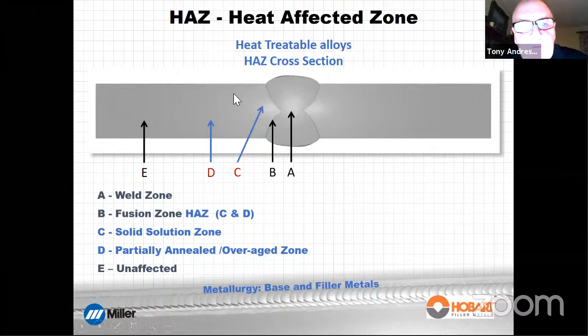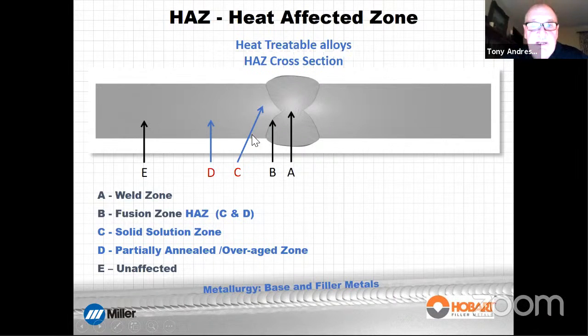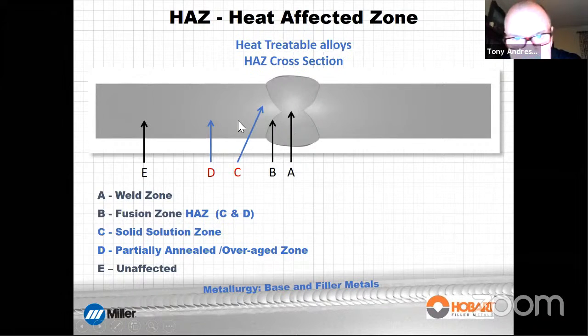So the rule here is to keep the heat down as low as possible if you want to get the best strength out of the base material after it's been welded. So stringer passes, don't weave, fast stringer passes, low heat input, watch the interpass temperature and preheat. Don't preheat really if you can avoid it, and you usually can. You don't need to preheat aluminum.